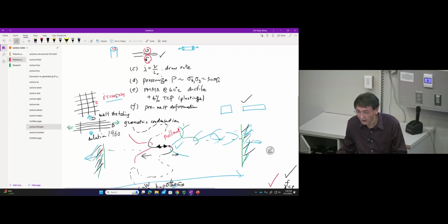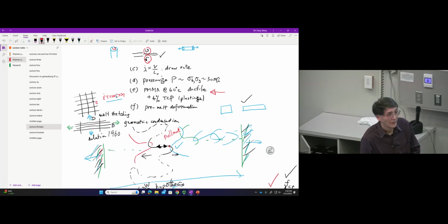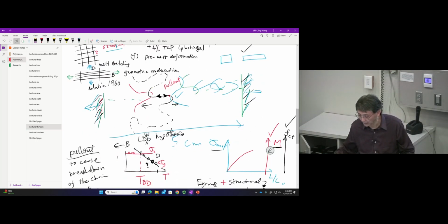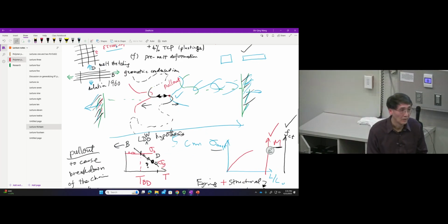Let me tell you one part that you already should be intrigued by. I mentioned this as one of the 6 factors. In fact, this is a factor that was only discovered after we had the picture. In other words, this is not a widely documented effect. Let me explain this effect one more time. You bring your PMMA to 60 degrees, which apparently is above the BDT. You are enjoying a ductile PMMA. At 60 degrees, it's warm enough, it's ductile.